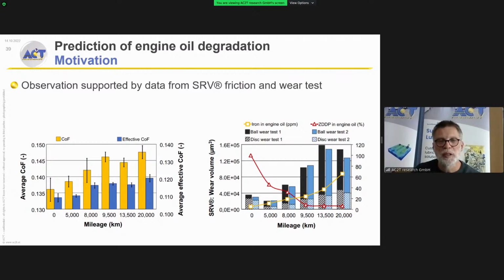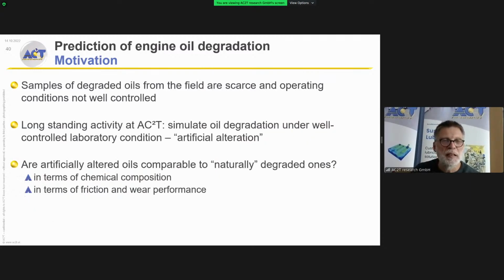And here you have also plotted the concentration of ZDDP in the oil, and in contrast, the iron content in the engine oil will rise because of increased wear. This is the observation on a qualitative level, and the motivation is then to devise some statistics or some procedure where you can model this data and give some more quantitative correlations between the different aging states of the oil.